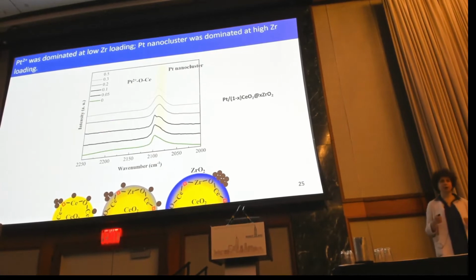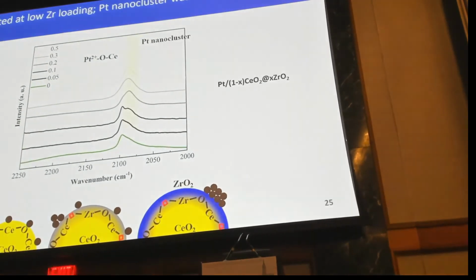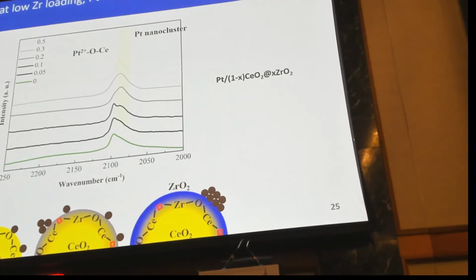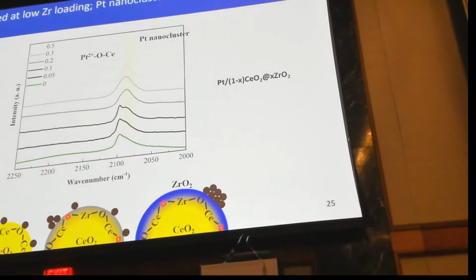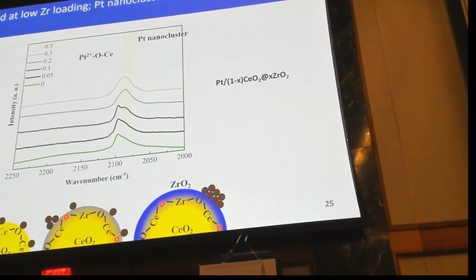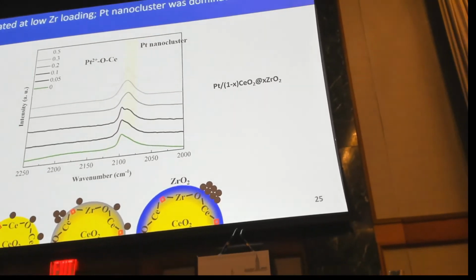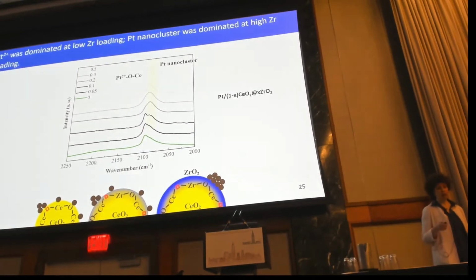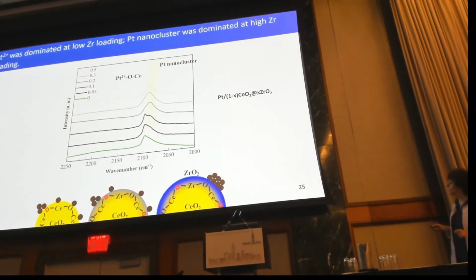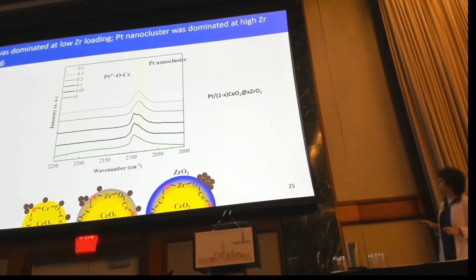So we did CO DRIFTS over all standard catalysts. Here what we see is that from bottom to top, we increase the zirconium content. So here this green spectrum is for the platinum support on the ceria spheres. And what we see is that there is this high wave number peak that is attributed to platinum interacting with the ceria. Some people call it ionic platinum, some people call it atomically dispersed platinum, but in any case, this platinum is small in size.